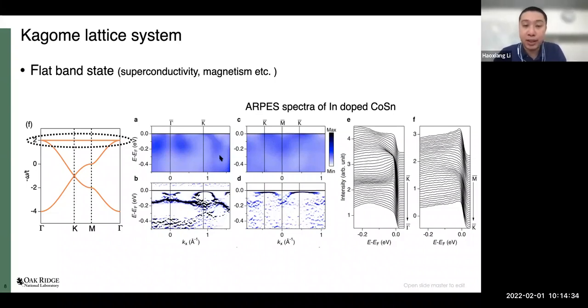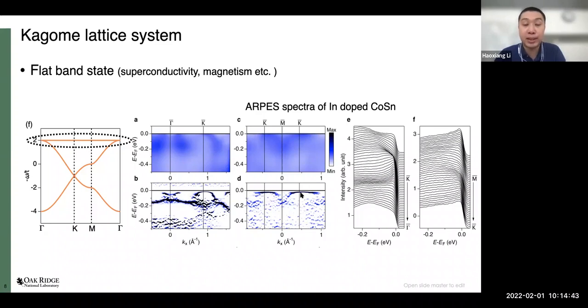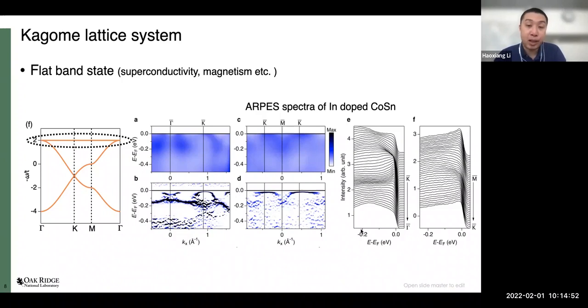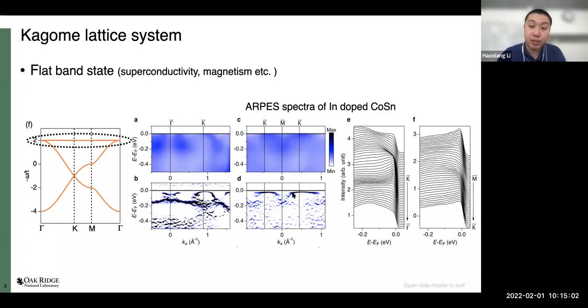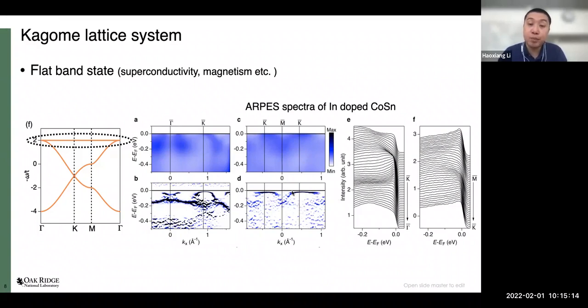Our recent study has also been looking for this flat band state with tunings — doping and compound tuning — to move the chemical potential toward the flat band state in some of these materials, with limited success, but we did achieve magnetism by simply tuning the flat band state in a non-magnetic parent compound. Here is an example of observed ARPES spectra showing some of these flat band features. It may not be perfectly flat in real life material compared to the toy tight-binding model, but it is still a flat band state covering a large area of the Brillouin zone.